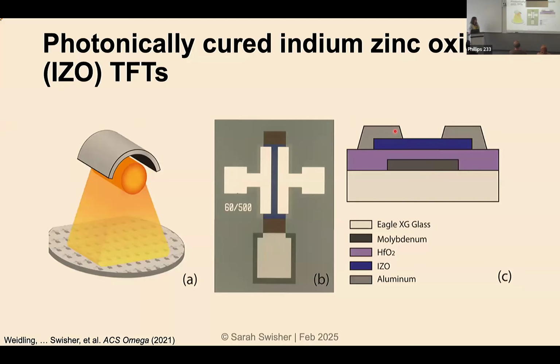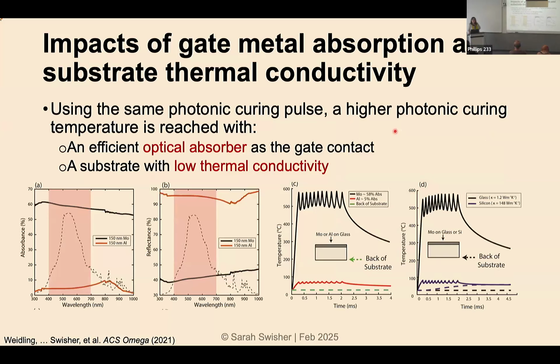So one of the things that we found out very quickly was that a lot of the early work that we'd seen from some other groups in this space used aluminum as the bottom gate. Well, it turns out aluminum is a wonderful mirror and a really bad absorber. And so what we showed in some of our early work here is that if you use aluminum as your bottom gate, you are absorbing very, very little of the light. And as a result, the temperature that you will reach on the surface is incredibly low. Most of that energy is just getting reflected. And so by choosing a bottom gate that is an excellent absorber like molybdenum, with the same flash pulse, we are going to see a temperature of around 500 degrees instead of a temperature below 100. So first choice, you have to choose your materials wisely, right?